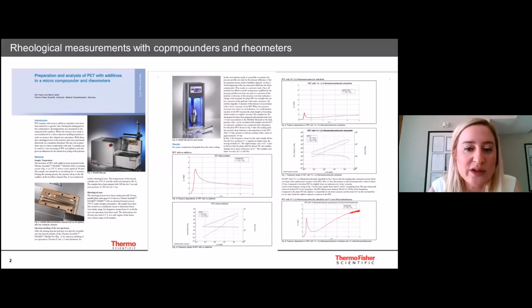So we can test directly in the mini compounder the PET with no additives and with the 2 different additives and see the pressure graphs, how pressure differs during the processing. And we can also have this oscillation data afterwards, as we saw in the video. We can prepare discs for parallel plates, in this application 20 millimeter parallel plates, and the data is taken from the HAAKE Mars 60 advanced rheometer system.